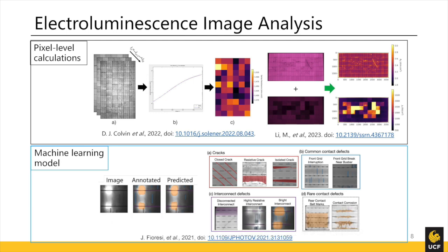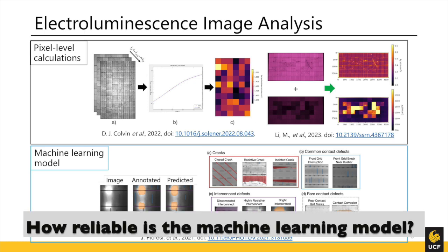Yeah, that's a good question. So we fed it 17,000 annotated images, cell images like here, and we saw around 90% accuracy. Now the accuracies are different depending on what classes of defects we use. A large part of what impacts that is class imbalance.